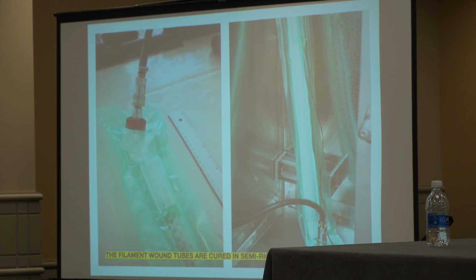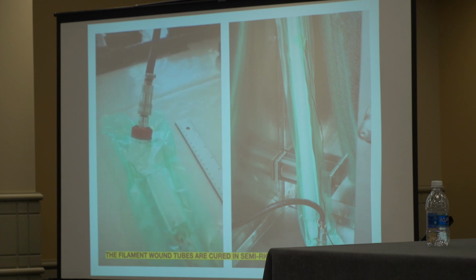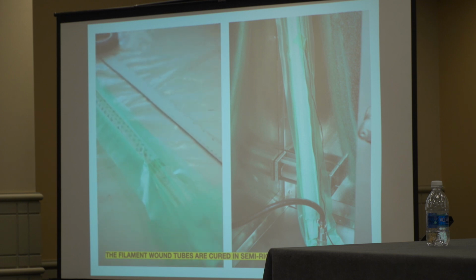So I have an electric heating element in the oven and a fan, and then there's a PID controller where I can set the ramp rate of the oven, and I can log it on a per tube basis. So I have a record of the frame curing. There are little thermistors constantly checking the temperature in the oven, and I can tape one to the tube itself. So it's a pretty controlled curing environment. And then it cures under vacuum the whole time, so there's a vacuum running that ensures the tube is under pressure the whole time.